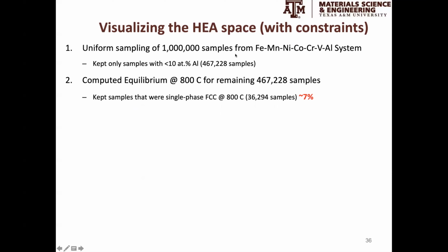When, out of these alloys, we then look at alloys that were single phase FCC at 800 Celsius, we see that the total number is reduced significantly to 7%. So the alloys that are FCC at 800 Celsius with less than 10% aluminum are just a small fraction of the space.